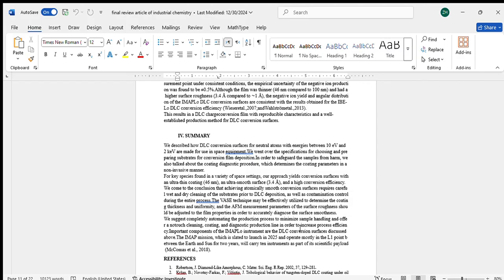Ultra thin and ultra smooth coatings. The DLC coatings have a thickness of 46 nanometers and a surface roughness of 3.4 angstrom, which is ultra smooth. This smoothness is essential for the surfaces to function properly in space instruments, where smoothness and uniformity play a crucial role in ion conversion efficiency. Importance of cleaning and contamination control: the key to achieving smooth conversion surfaces lies in the careful cleaning of the substrate before deposition and contamination control throughout the coating process.